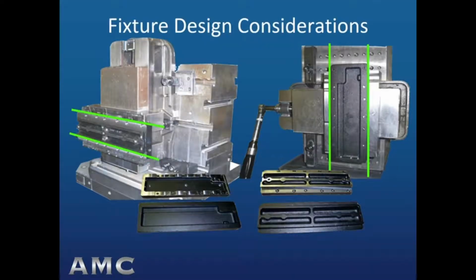To accomplish that, a go-no-go gauge is used by the machine operator to make sure that the casting's front surface is at the same elevation across both dovetails. The idea is expressed by the green lines along the fixture's dovetail clamping surfaces. Once that no-go gauge is satisfied, the casting can be fully clamped and the holes and the mill surfaces will be orientated correctly to the casting's as-cast datums.